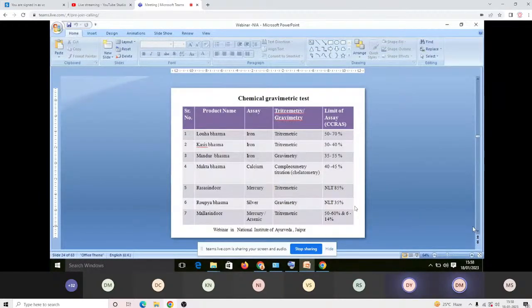The CCRAS limit for Loha bhasma is 50 to 70%, Kasis bhasma is 30 to 40%, and Mandur bhasma is 35 to 55%.